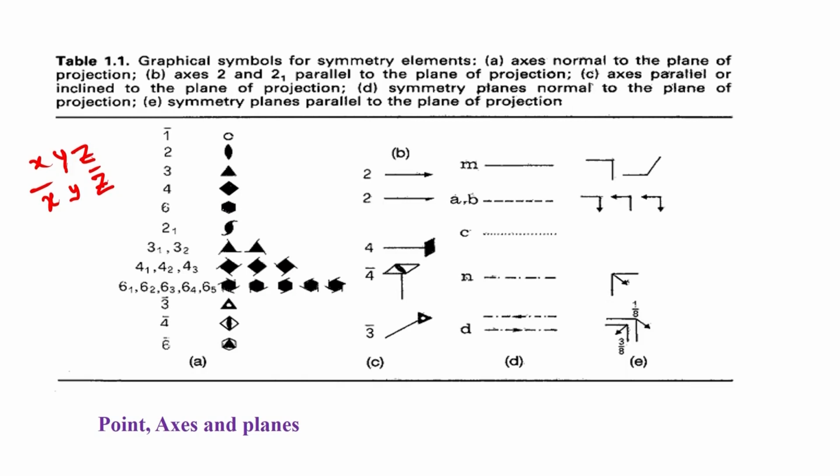So, the property of the point group is that when we operate this symmetry more than once, depending upon how many such operations are allowed by the symmetry which is present here. For example, in the case of a two-fold axis, x y z goes to minus x y minus z, and this again when operated will come back to x y z. So, there are two positions which will be generated by a two-fold symmetry operation, and these two positions are also referred to as equivalent points.